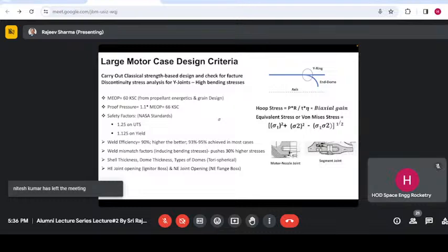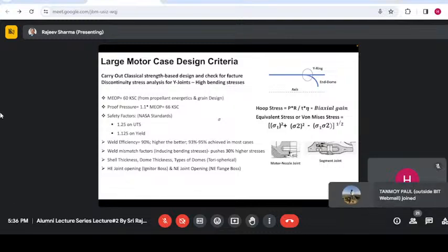The maraging steel is supplied in a lower strength, solution-annealed form, when the hardness of the material is around 34 HRC, 34 HRC max. I'm even surprised that I remember this number. But once you do the aging at around 485 degrees centigrade, the hardness of the material goes to around 55 HRC. You can't even do machining at that. The tools will break at that hardness level.